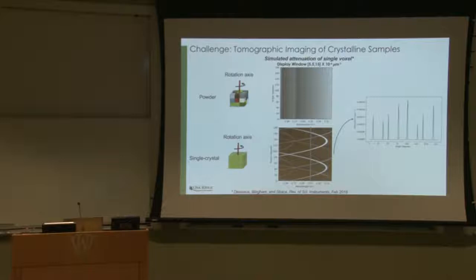To understand the challenge of doing computed tomography with single crystal samples, let's look at how the attenuation changes as a function of wavelength when an object is rotated in a neutron beam. What you're looking at is a simulation. Our group has developed some code for doing neutron transmission simulation. If you take a block of a powder and rotate it and plot the attenuation as a function of wavelength for different rotation angles, you can see that this doesn't change as a function of angle.